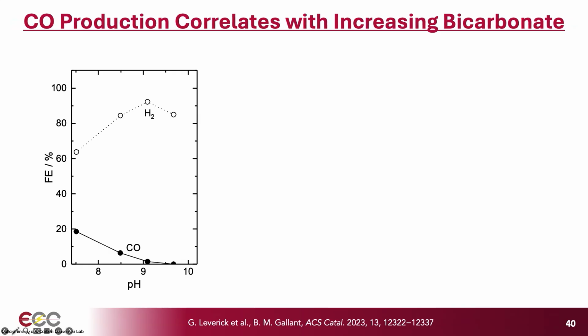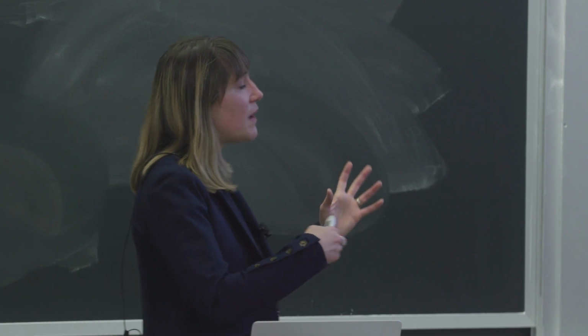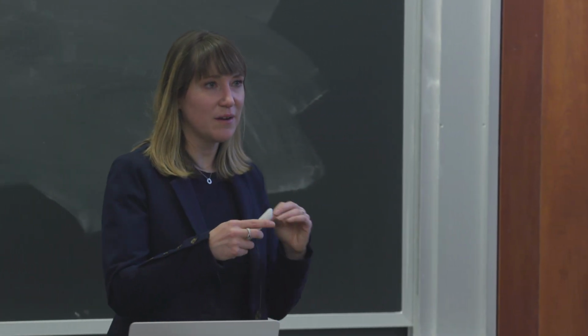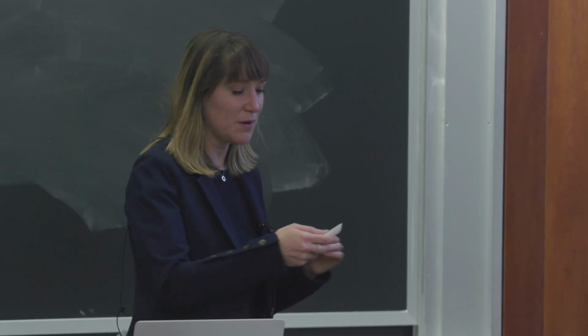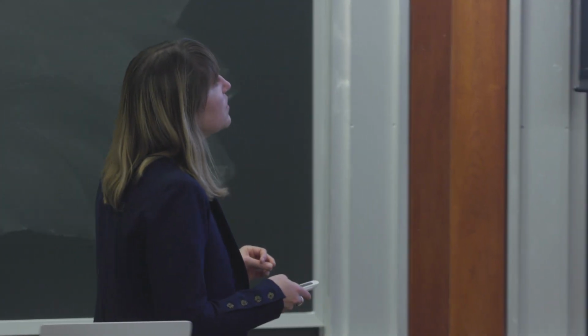So this graphs the product selectivity now upon reduction as a function of pH. And so you'll see at higher pH, as we go to lower pH, you start to see the selectivity to carbon monoxide increase, with the balance being hydrogen up here. So with this information now, we were interested in mapping this to the solution speciation to try to pull out which species appear to be correlating with the CO selectivity. And so that's shown here.